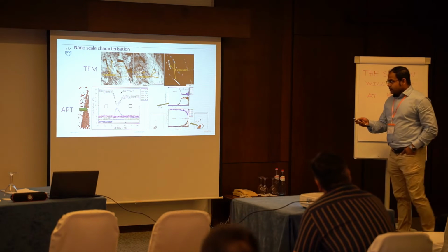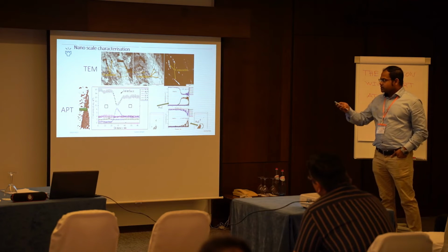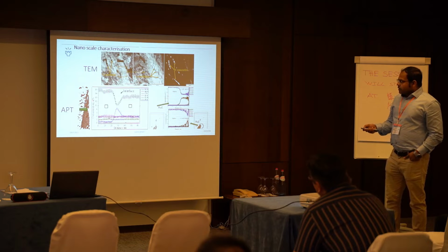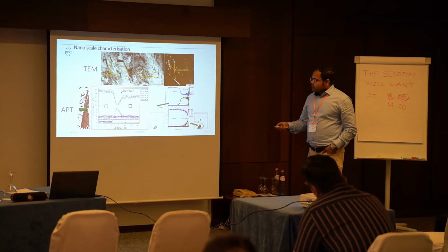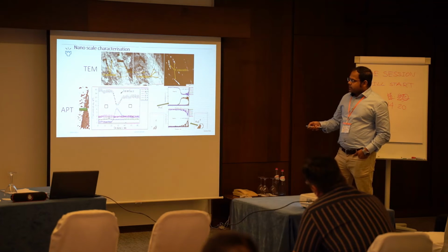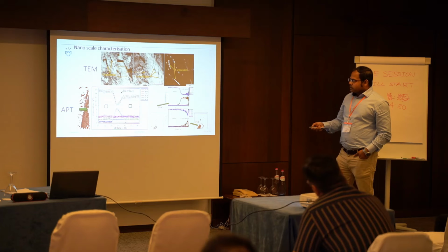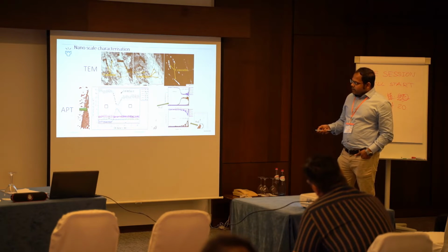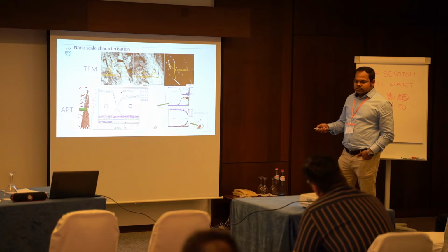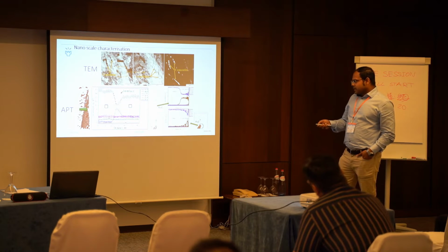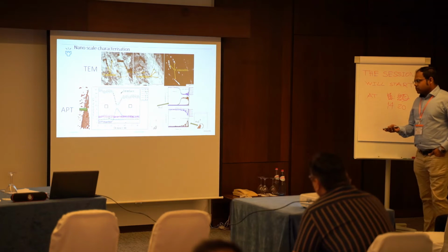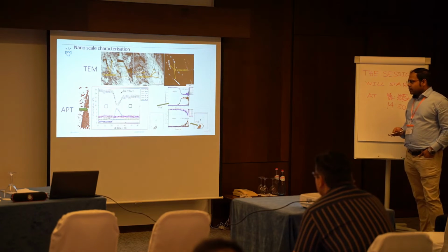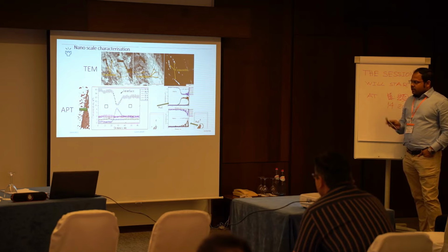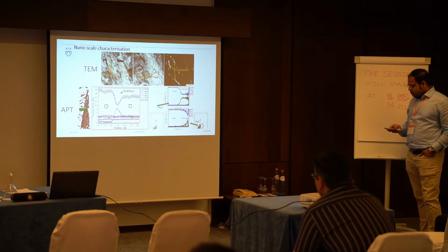And also another interesting thing we observed based on APT. Here you can see this low carbon regime is the martensitic phase, and the high carbon enriched regime signifies the retained austenite phase. And here you can see the carbon is not distributed homogeneously throughout the retained austenite. Mainly the carbon enrichment is quite high at the interface regime, and it's slightly lower within the matrix. That may be due to the dislocations introduced during thermomechanical processing that to some extent hinder the carbon partitioning within this retained austenite, but not much.